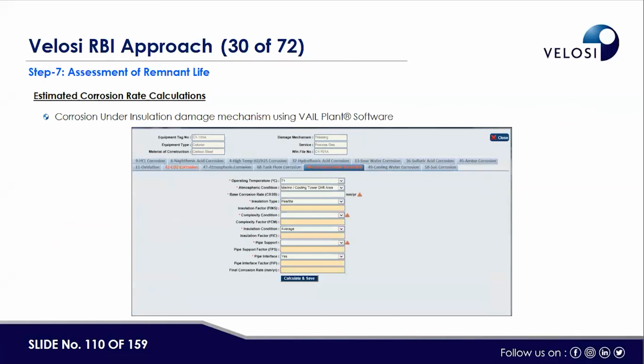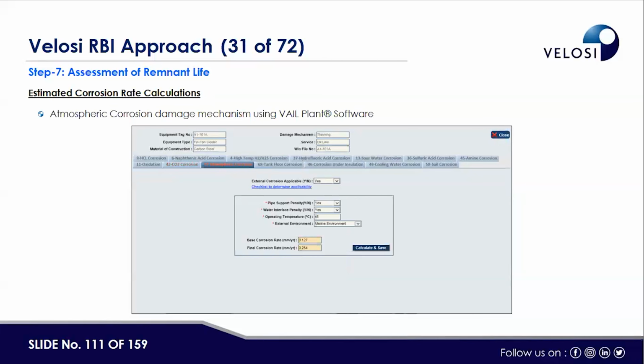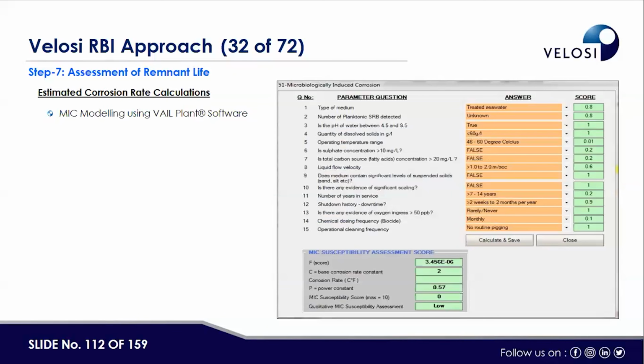This is corrosion under insulation, with similar parameters like type of coating, age, type, and condition of the insulation material. The model is available and can be used for estimation of the corrosion rate for CUI conditions. For atmospheric corrosion also, we have to provide the applicable conditions, painting conditions, and then it can calculate the corrosion rate. This is a live calculation. It is the same for MIC.